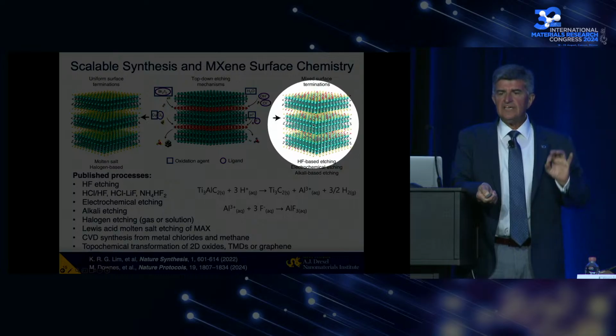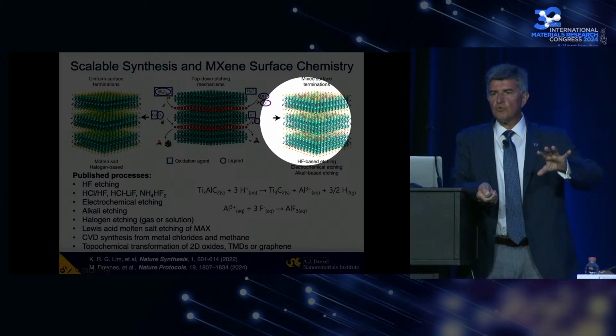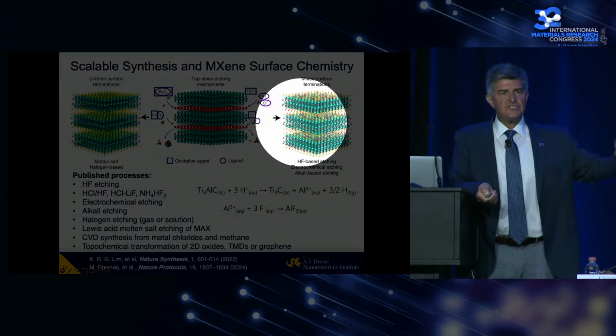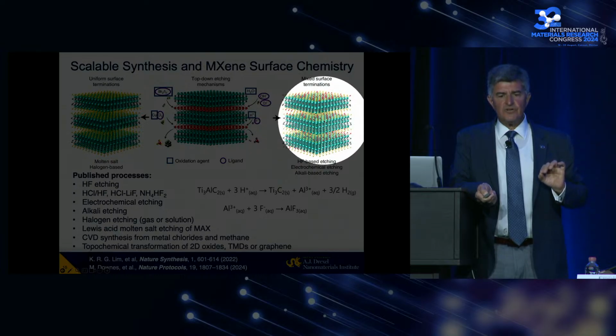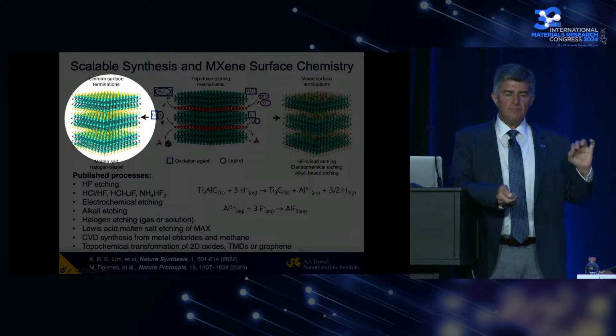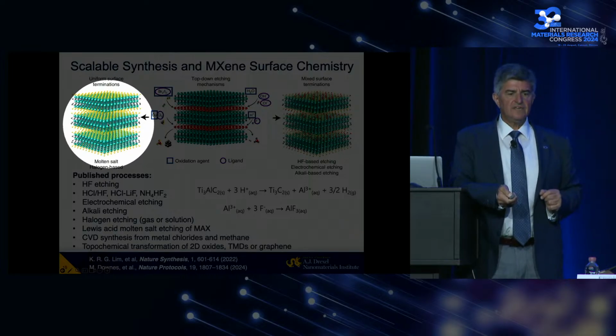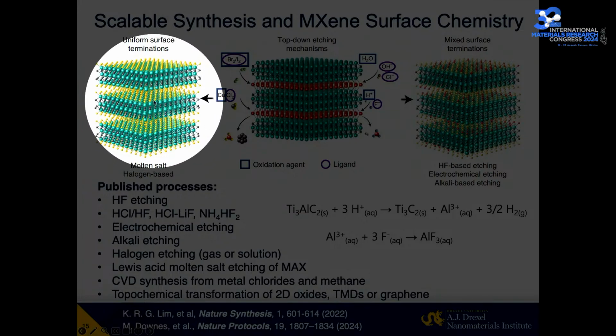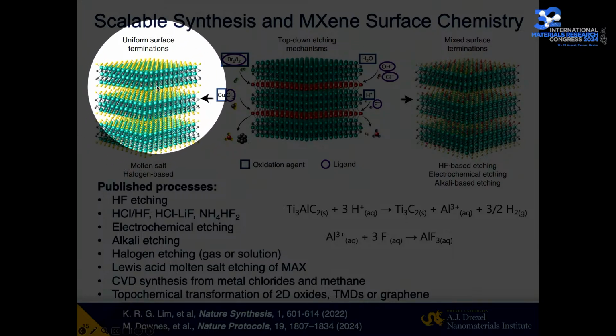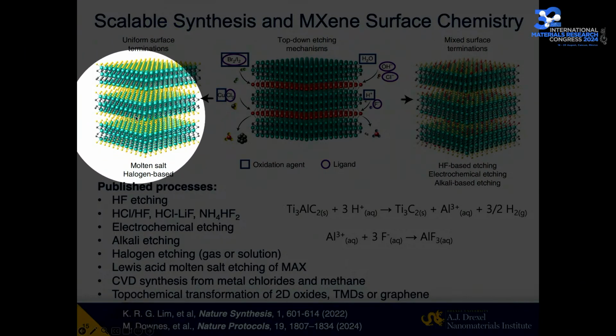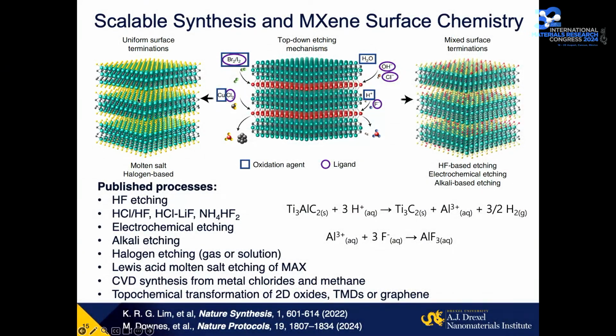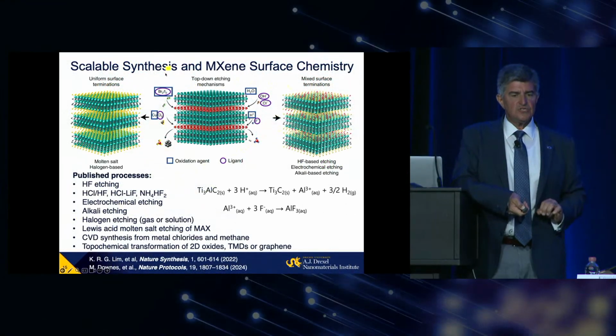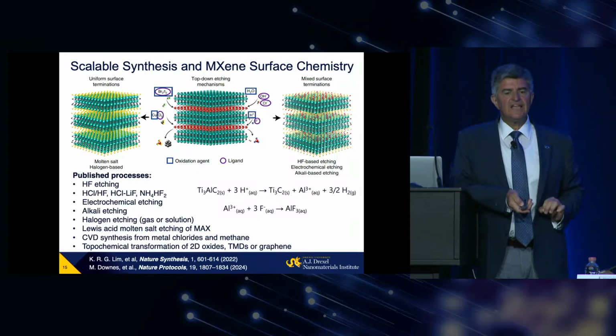When you use etching in aqueous solution, oxygen, hydroxyl groups, and halogens like fluorine and chlorine get on the surface. We get materials which are hydrophilic, easily dispersible in water, but with a mix of functional groups. If we use molten chloride, fluoride, or bromide salt, we get a material with halogen surface termination, very uniform. Metal-halogen bonds are easier to break. You can do surface functionalization after that with organic groups or other elements like chalcogens. You get the same terminations when you use chemical vapor deposition or halogen etching of MAX phases. So again, by processing, we largely determine the properties of these materials.